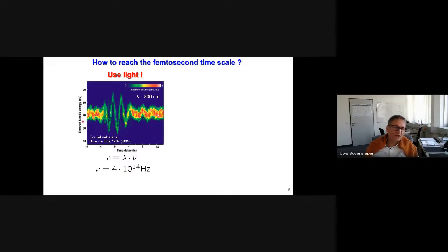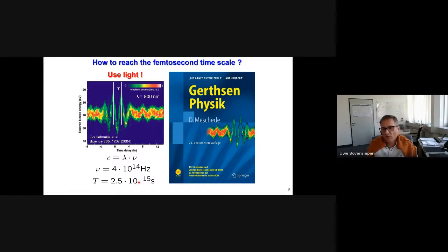And what you see here on the vertical scale is the electronic kinetic energy, measured using photoelectron spectroscopy after emitting photoelectrons and then letting them interact with the electric field of the laser pulse. And we can read off the periodicity of this light, which is 2.5 times 10 to the minus 15 seconds. So you can clearly see the femtosecond time scale. And this was very seminal work, which also made it into a well-known physics textbook here in German language.